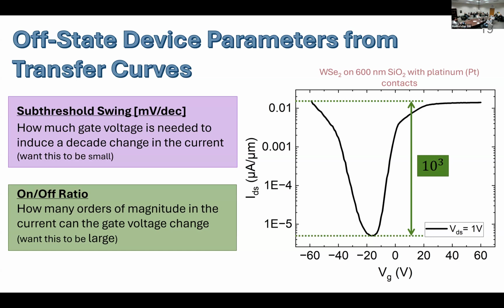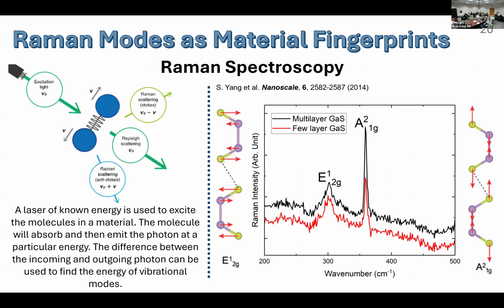And now that we're done with the electronic characteristics and how to obtain device parameters from the transfer curves, we can look at the different ways in which we characterize their structural properties. One way we do it is using Raman spectroscopy. So in this method, you shine a light, the light will be absorbed by the molecules in your system. The outcoming light will give you information about the vibrational modes in the crystal. We use this for a couple of different reasons. So our 2D materials come in many different polytypes. The polytypes are not easy to identify based on optical images, which is why it's important to use alternative methods to characterize their structure. So by looking at the distinct modes of each polytype, we are able to identify one polytype from another.